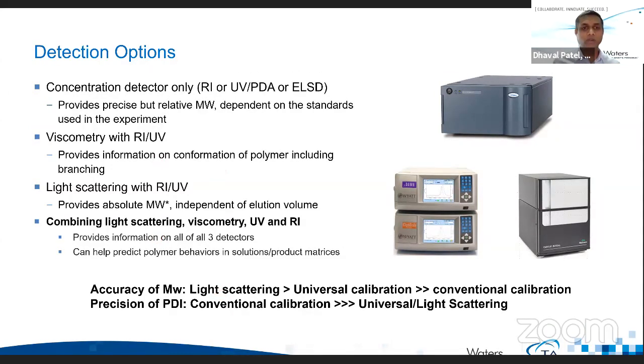And why are we talking about different detectors? You have to keep in mind that different techniques give you different information. If you want to get accurate molecular weight, of course, light scattering would give you more accurate information. However, it's not a precise measurement of polydispersity index. So conventional techniques such as the refractive index detector would give you a more precise measurement of polydispersity index versus light scattering or other detectors. That's why the choice of detector depends on your ultimate objective of analysis.